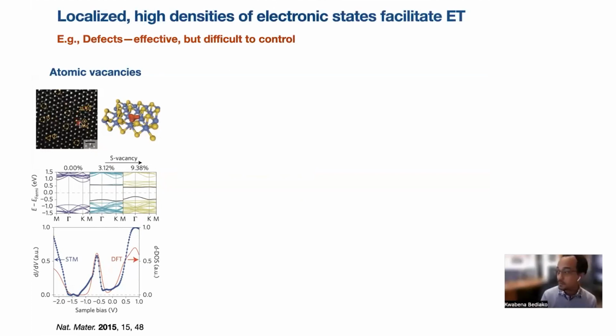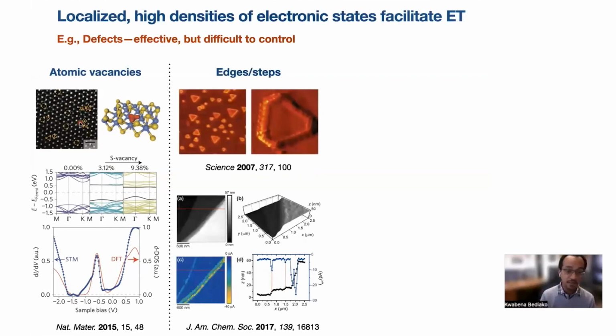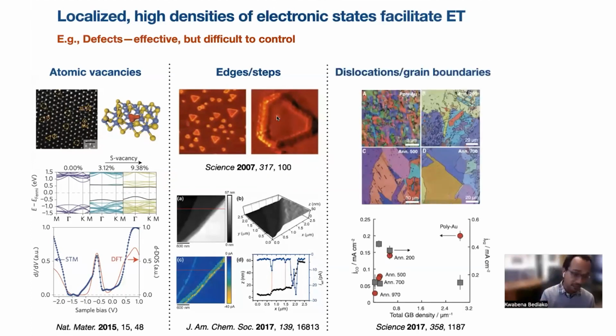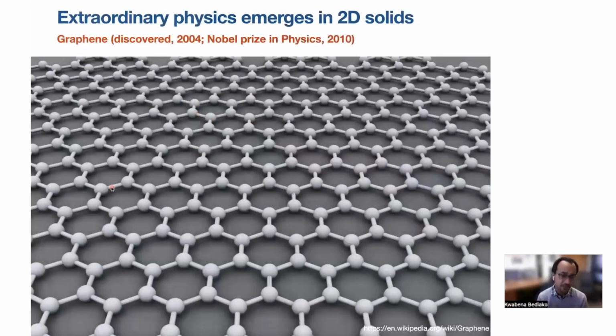Likewise, steps and edges of materials are commonly implicated as the active sites in interfacial catalysis. And then another example is in the case of dislocations and grain boundaries that actually have very interesting selectivity implications. So the point of all this is to say that defects, which we know can have very different local electronic structure from the pristine or bulk, tend to be reactive hotspots in interfacial charge transfer reactions because they tend to have these localized electronic states, but they're very difficult to control at an atomic level. And so my group uses two-dimensional materials, and ultimately our goal is to say, can we develop very tunable models for interfacial charge transfer that can teach us something new.